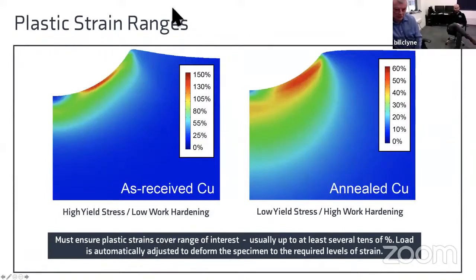So both of these are going to a depth of, well, a few hundred microns, and they're different materials, so that affects the strain range you get. This is a material not exhibiting much work hardening, so you get quite high strains, quite localized. You also get a big pileup. If you have a material with more work hardening, then the plastic strain gets diffused over a larger region and there's a bit less pile up. But in both cases, you can see that we're generating strains up into at least several tens of %. And that's the kind of thing you need to do.